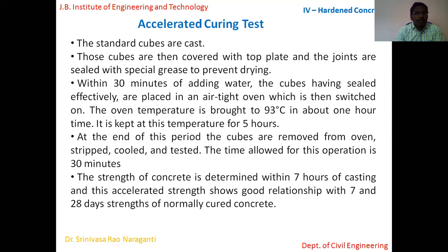The overall time, from the time you start mixing the ingredients to the time you start performing the test, should not be more than 7 hours. Within 7 hours, you start doing the testing. We'll cover completely how to do the compression test on concrete, but for now, understand that we use a cube. Then we put the cube on the CTM, the compression testing machine. You break the cube and note down the load at which it fails. Load divided by cross-sectional area will give you the compressive strength.